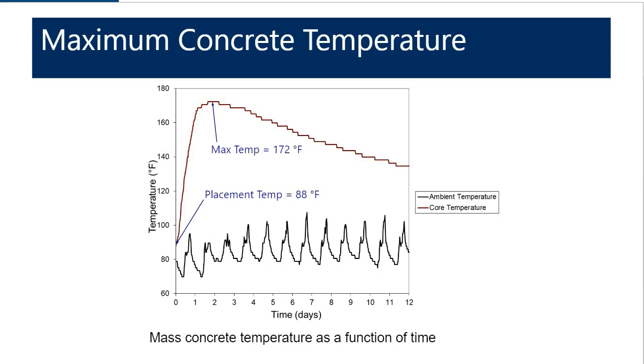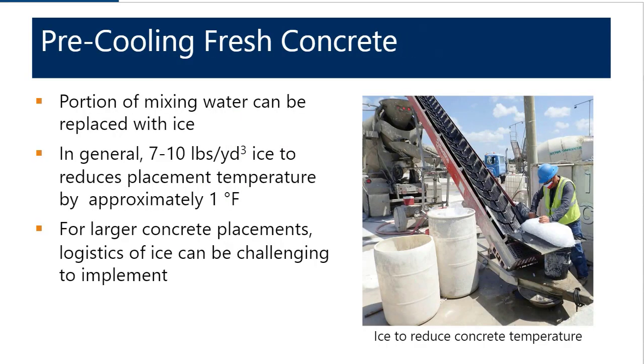And so pre-cooling of fresh concrete can be done in a variety of different ways. And so we're going to talk about a few of those. One of the simplest ways of pre-cooling fresh concrete is through the addition of ice. And so the general rule of thumb is about 7 to 10 pounds of ice per cubic yard can reduce the placement temperature by approximately 1 degree. And this will vary depending upon the time of year, and if those bags of ice are actually bags of ice when they're loaded into the truck, or if they've started melting.